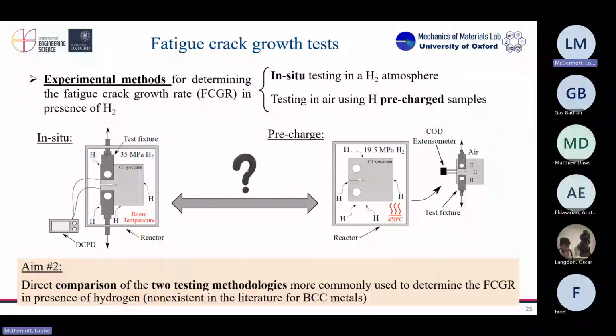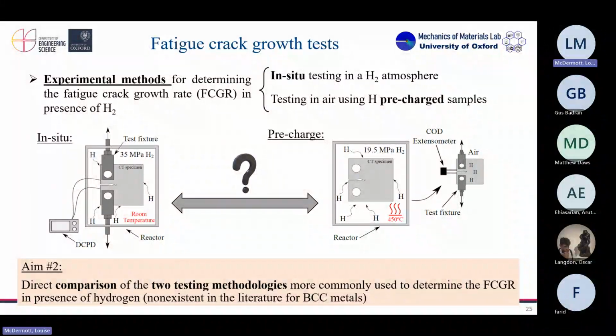And we have two ways of characterizing fatigue in metals. If you think about what we did before for the TDS, we can charge our sample. This is a sample that we use to test fatigue crack growth. So you can charge it and then test it mechanically, and do fatigue in air. So you fill the sample with hydrogen and then you do fatigue in air. Or you can do fatigue in a hydrogen environment. That's more similar to a real case scenario, right? Like we have a pipe that's carrying hydrogen, and then you have fatigue loads.